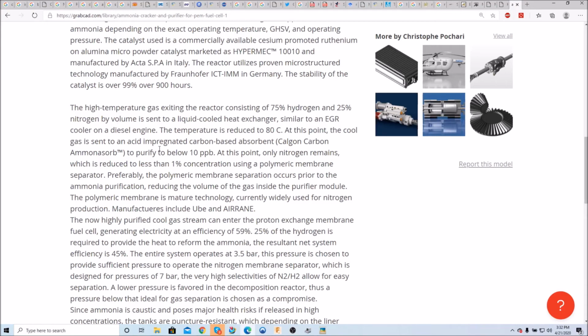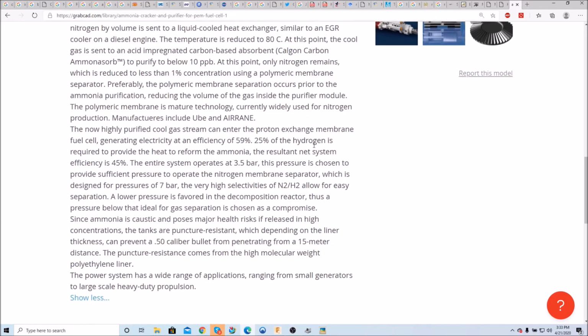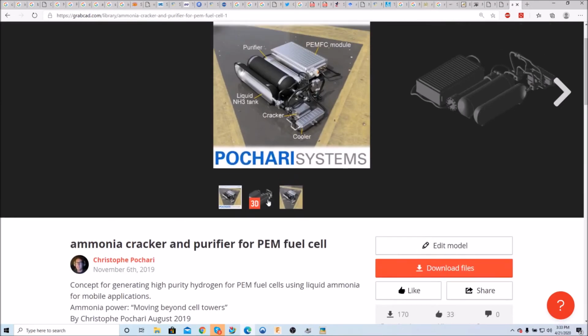The cool gas is sent to an acid impregnated carbon base absorbent that's manufactured by Calgon Carbon, Ammonasorb. That's hard to pronounce. To purify below 10 parts per billion. Okay, we remove our nitrogen until we only have 1% nitrogen concentration using a polymeric membrane. The now highly purified cool gas stream can enter the proton exchange membrane fuel cell. 25% hydrogen is required to provide the heat to form the ammonia. Net efficiency is 45%, and we have our puncture-resistant, ultra-high molecular weight polyethylene tank.